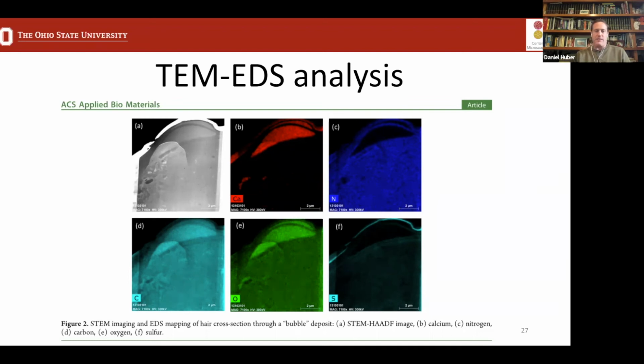And so in section A, we've got the high angle annular dark field detector, HAADF detector, forming our STEM image. And then in B, we're going to see a map of calcium K alpha emission. In C is nitrogen, D is carbon, oxygen, and sulfur. What we can see here is there's a considerable amount of calcium in this bubble, but not necessarily nitrogen, and sulfur is found on the outside surface of the sample. So what is that going to tell us?